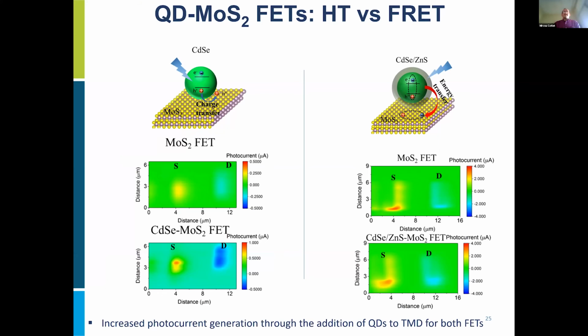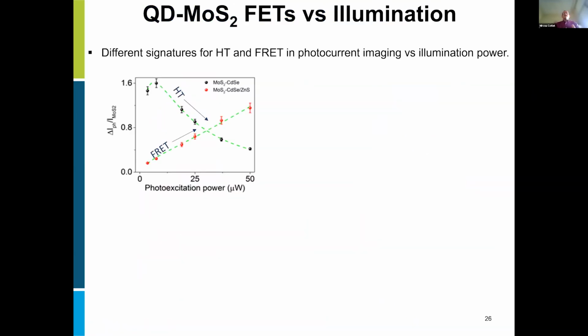We can do, like I said, photocurrent imaging, and we see that from the pristine device that has only the 2D material to the hybrid device, or hybrid structure, we get an increase in the photocurrent. So addition of the quantum dots, in both cases, core and core shell, will show an improvement in the created photocurrent.